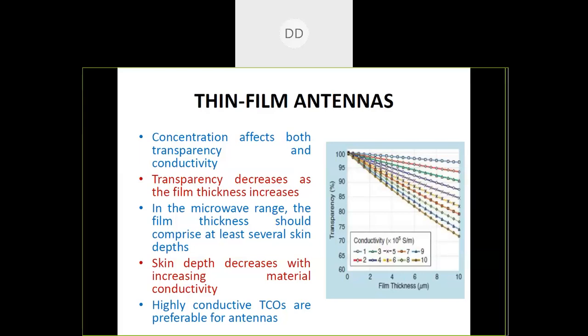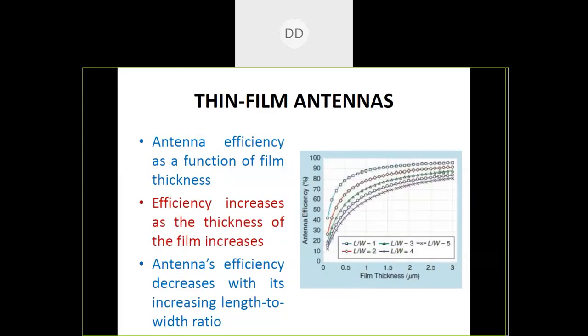And these affect the conductivity further. So instead of simply taking those values, conductivity has been taken into account. We can see that concentration affects both transparency and conductivity. Understanding the relationship between these is very important if we want to use this material for the design of antennas. Highly conductive TCOs are preferable for antennas, but skin depth decreases with increasing material conductivity. So all these factors we need to keep in mind when we want to design these antennas.